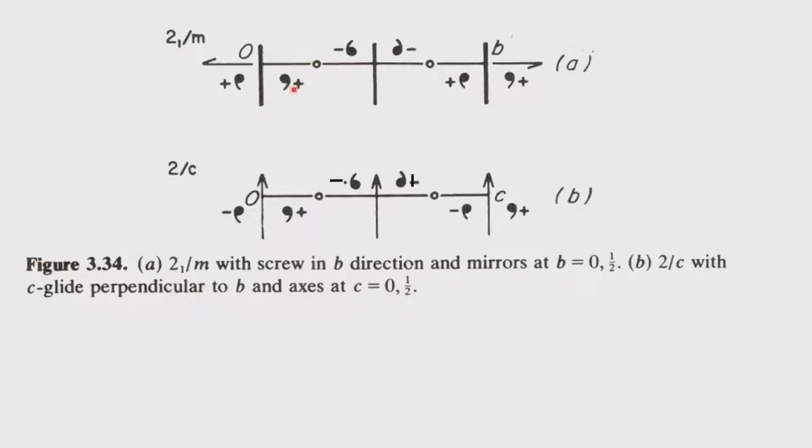In other words, if you take this point as x y z and you operate the 2 1 symmetry on this one, you will go to that point which is what? x bar y z bar. So, you get the x bar y z bar, you get the x y z, and the fact that this has happened is because of the operation of the 2 1 screw.